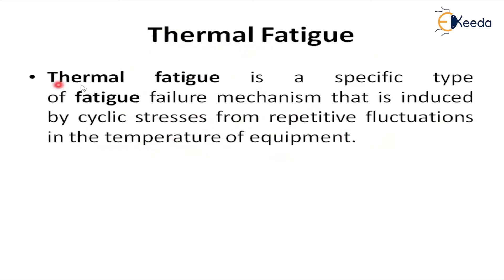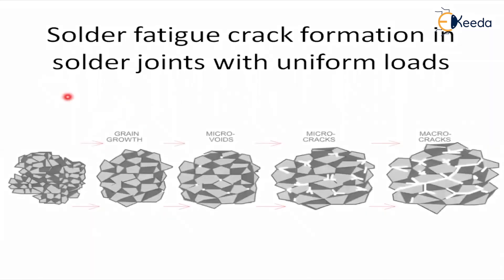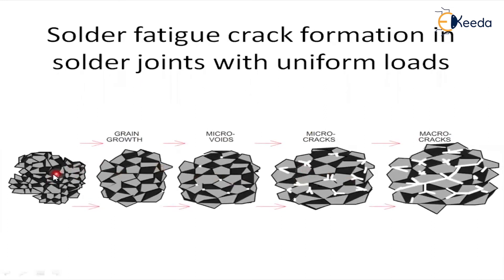The degree of damage is mainly affected by the magnitude and frequency of the temperature swings — how much temperature is applied and at what frequency. Observe this picture showing solder fatigue: crack formation in solder joints with uniform loads. Grain growth and micro-voids are caused by the thermal effect, and micro-voids are converted into macro-cracks. This is the result of temperature effects on material.